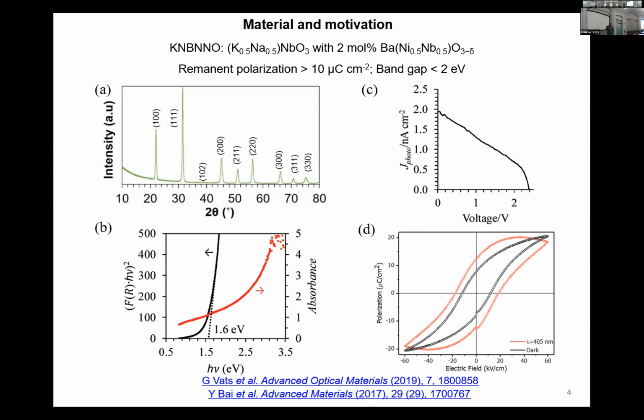And when I expose this to a wavelength of 405 nanometers with very low energy of around 5 milliwatt, then the loop expands a bit. There is a change in the coercive field and the remnant polarization. It looks a bit leaky as well, but we'll come to that in a bit.